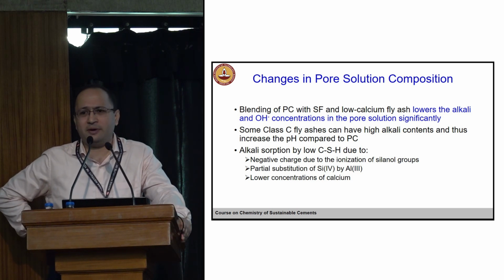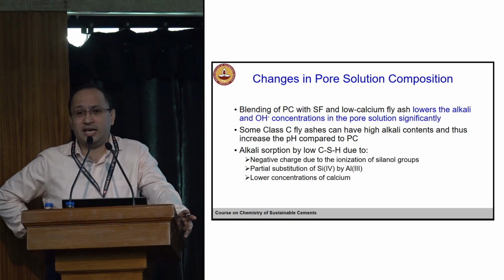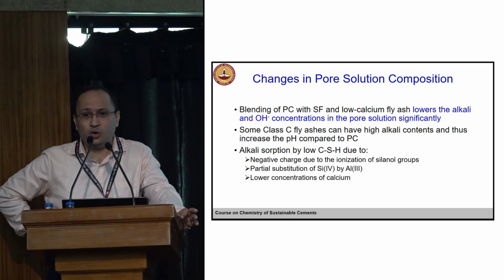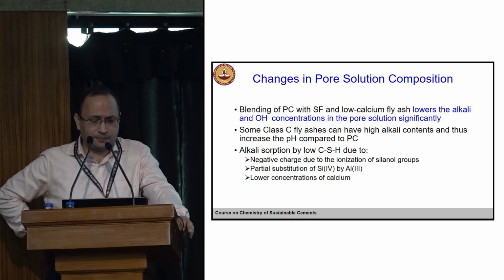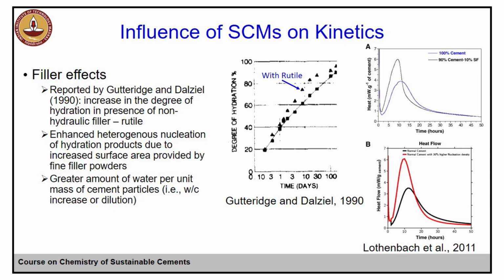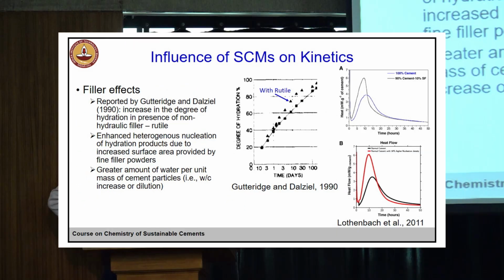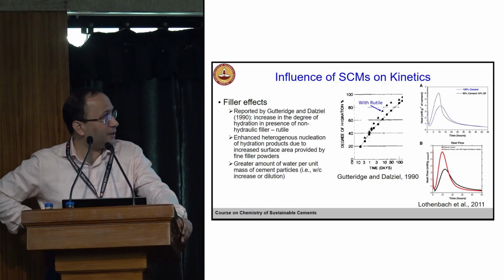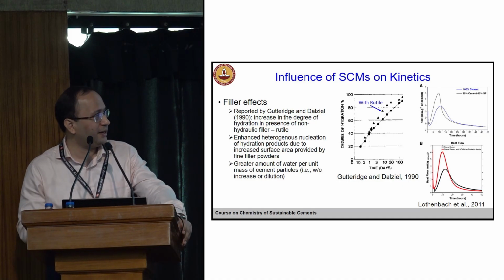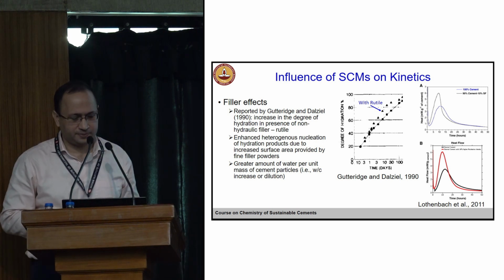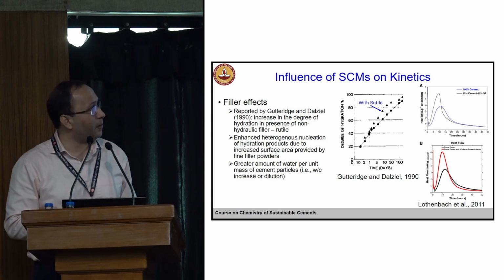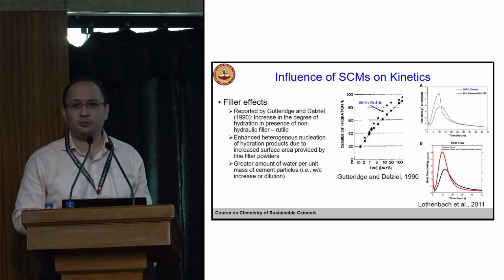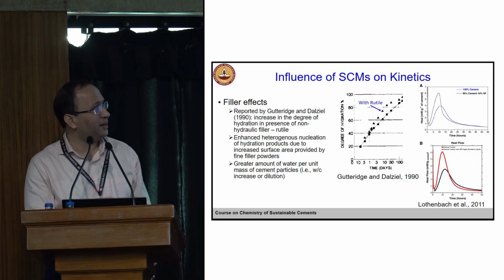But if you have an SCM which has high alkali content, then you may not see that much drop initially. This we know, and this is fine. This is with respect to CSH. Now another thing is the filler effect. All of you must have heard of this filler effect. There was a landmark study in 1990 by Gutteridge and Dalziel. What they showed is, if you just add rutile, what is rutile? Titanium oxide, an inert material.